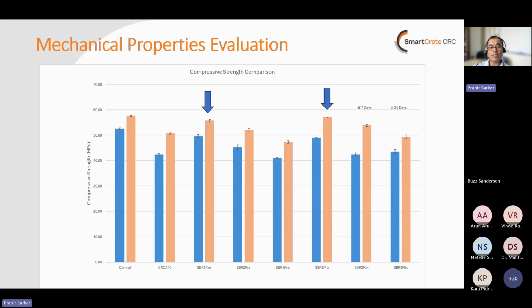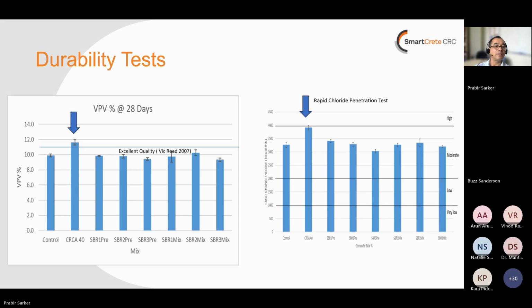But when the SBR latex is increased beyond 1%, we can see a decline in the compressive strength. So we think that 1% may be a good percentage of SBR latex that can be tried to improve the aggregate properties.